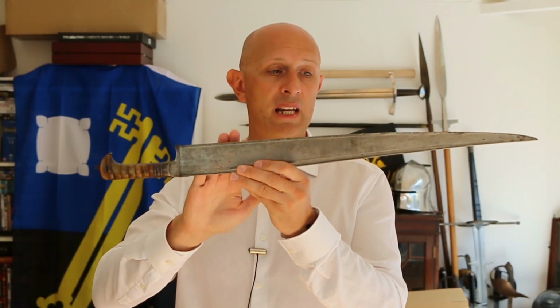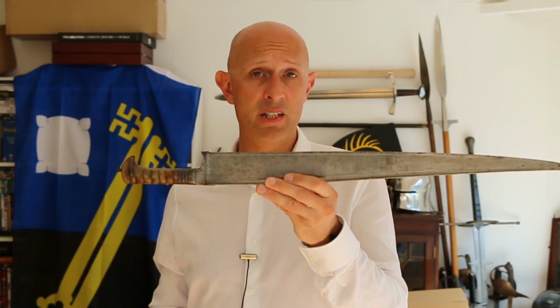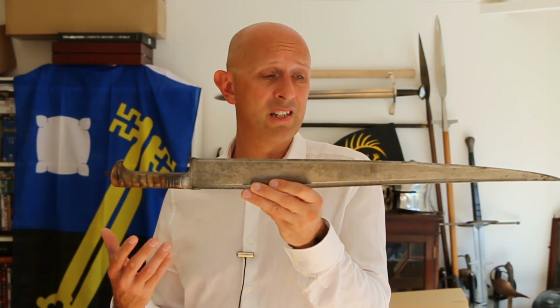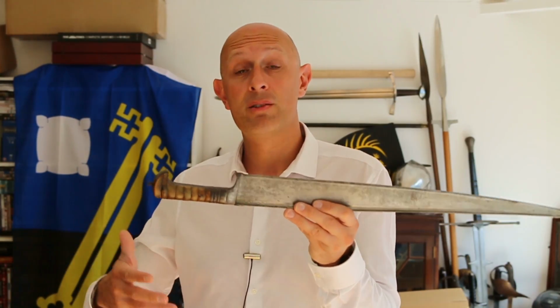In Afghanistan, they had to make use of what they had, okay? And so the steel quality is often quite poor, and they often seem not to be heat treated. I don't know why. Maybe it's because they didn't have a high enough carbon content to quench them. Maybe it's because they didn't trust the integrity of the steel, and if quenched, you'd rather have a weapon that bent rather than snapped. I don't know, okay, but very often these are soft.